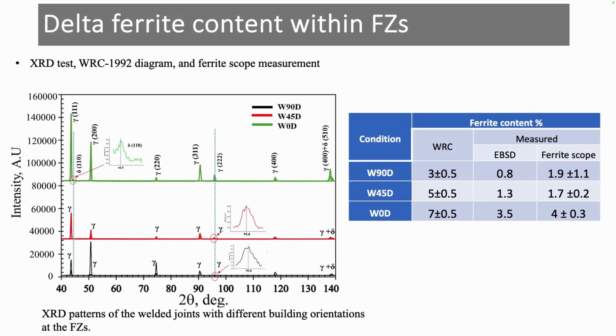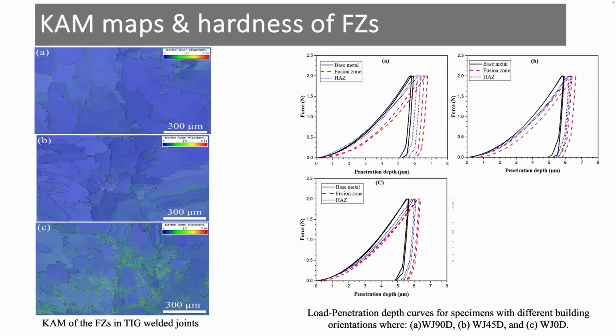We found one peak here in the 90-degree, which was not found in 45 and 0 degree, in addition to using Feritscope to measure the volume fraction of the delta ferrite. It was increasing with increasing the cooling rate. So therefore, the WJ0 will display volume fraction of delta ferrite more than W90D and 45D. And here also the KAM displaying that when we increase the cooling rate, then we will have more misorientations.